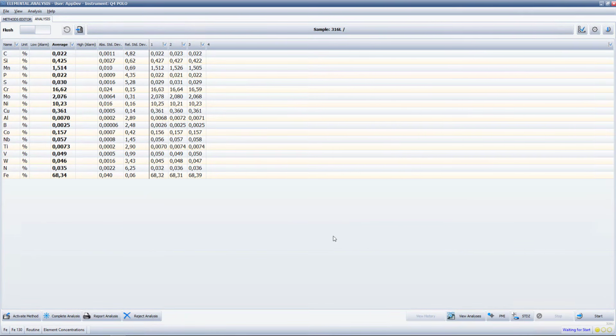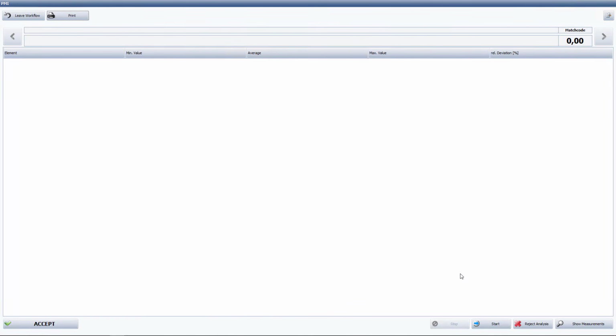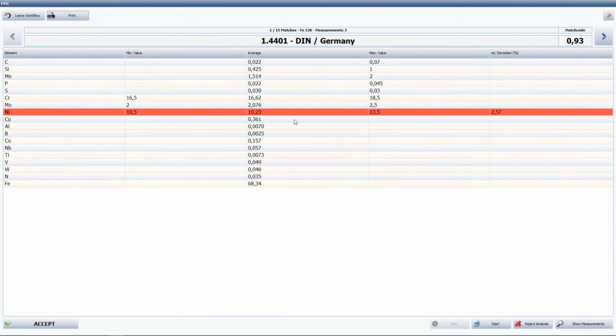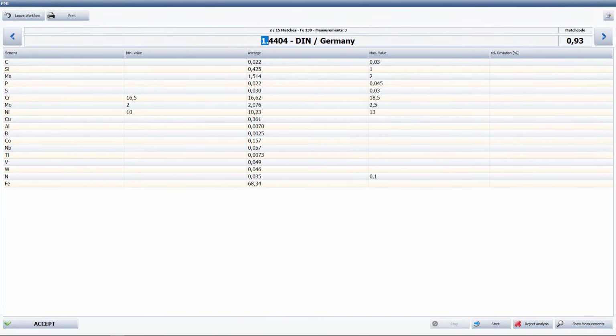Now that the analysis has been completed, I simply press the PMI button to do a positive material identification. And now Elemental Suite is looking for the matching grades in the total material database. And the first matching grade is 1.4401, which has minimum 10.5% of nickel. And at the end of our analysis, we got 10.23. That's why it's highlighted in red. And the next matching grade is 1.4404, which is exactly the same grade that we analyzed together. So I press Leave Workflow to go back to my analysis screen.